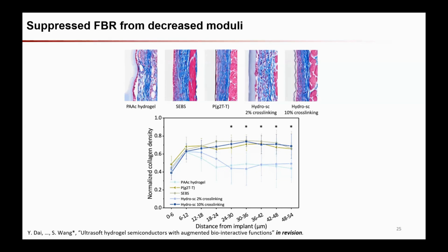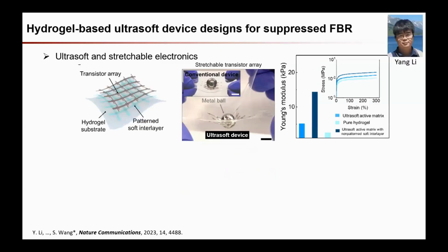So I'd like to mainly highlight one comparison. That is this semiconducting polymer with two varied cross-linking ratios. That led to two different levels of mechanical property, differing by only one order of magnitude. The result of the implantation shows that this is the higher cross-linking ratio, with the collagen density right here, and this is the lower cross-linking ratio. Even though they are just thin films on the surface, this modulus difference creates a major difference in the foreign body response.